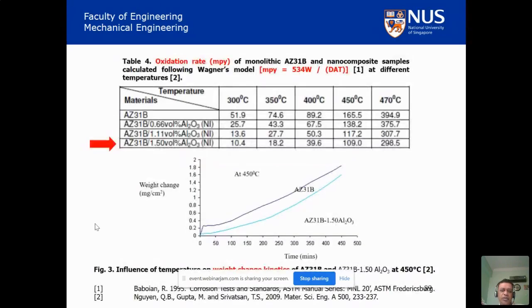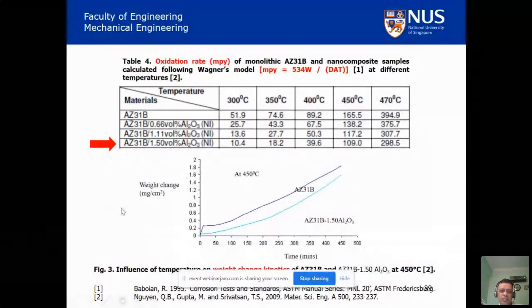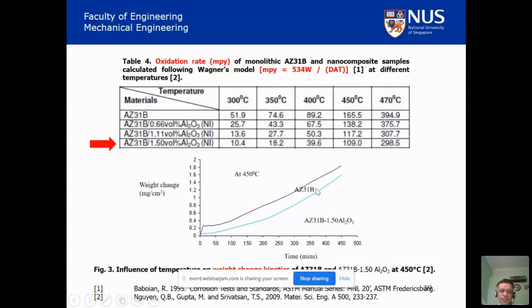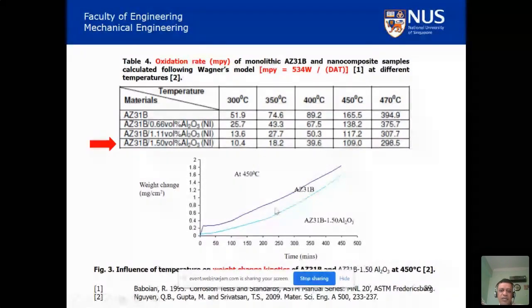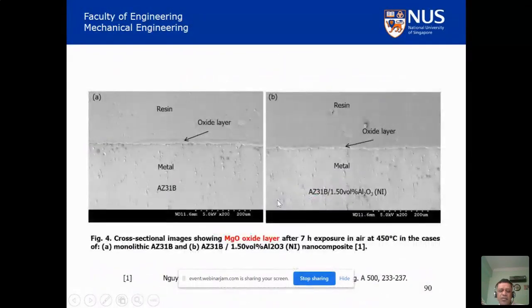So we carried out the dry corrosion characterization of the material, and we see that for the case of the composite, this light blue color curve here is always lower than that of the base material. And this is attributed to the microstructural refinement, which comes because of the presence of nano reinforcement. Now in this picture, what you see on the right hand side is that the thickness of the oxide layer is thin, and much more compact than the base material.